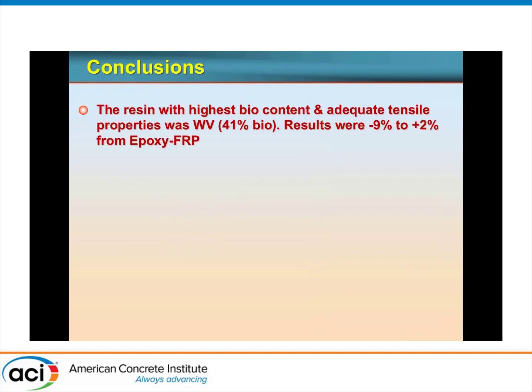So at this point, the conclusions from this study are that the most promising resin, with the highest bio content of 41% and at the same time adequate tensile properties, was the resin extracted from wood and vegetable byproducts. It resulted in tensile properties and moduli and so forth ranging from -9 to +2% compared to epoxy for glass and carbon.